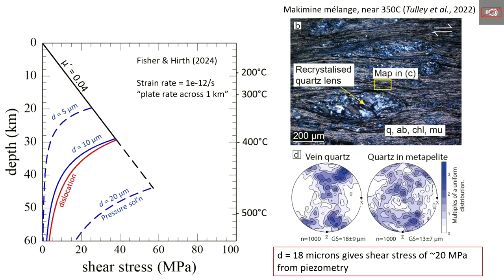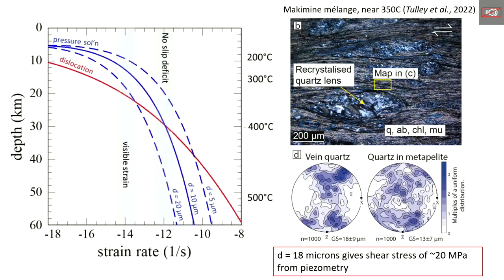So the stress state you get from the grain size analysis here is around 20 MPa, so somewhere kind of in the ballpark of where we're thinking this is going to happen. And if we go onto this plot at 350, we see the grain size in the metapelite is as small as 7 and as large as 20. So in this range, it's deforming faster than the dislocation creep, which is boudinaged, and so it's consistent. So the rocks from the Shimanto belt show this transition that matched where we started from.